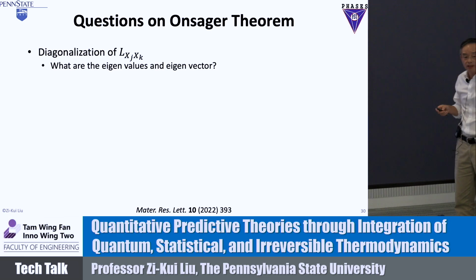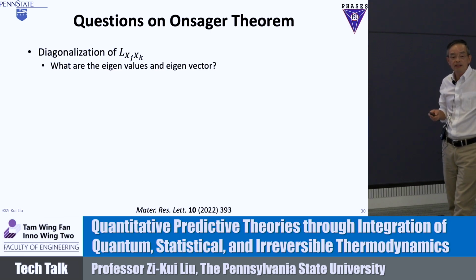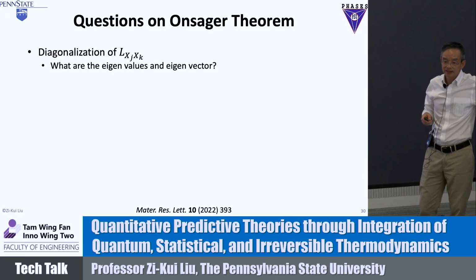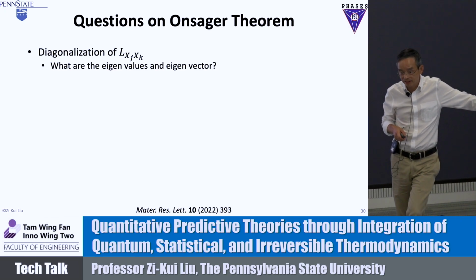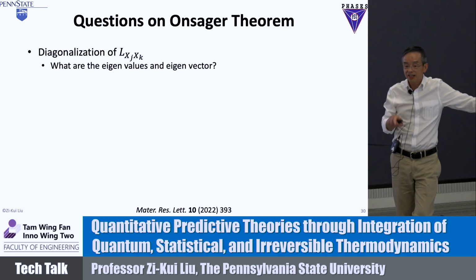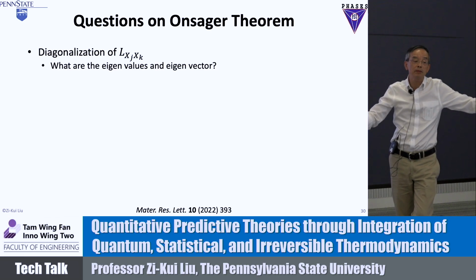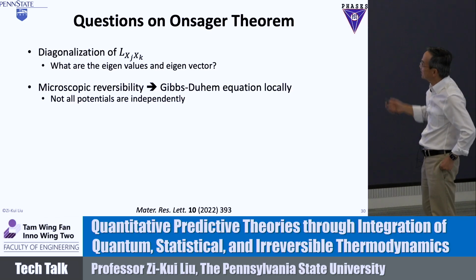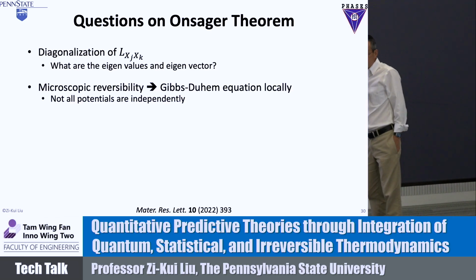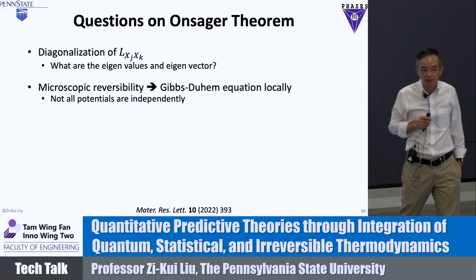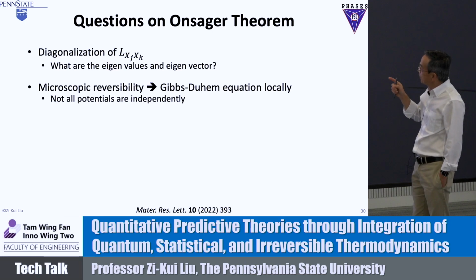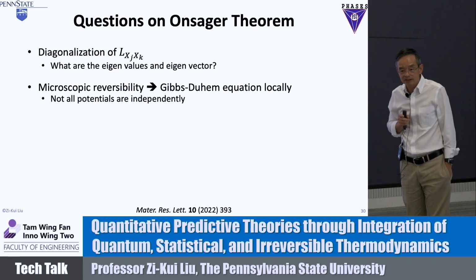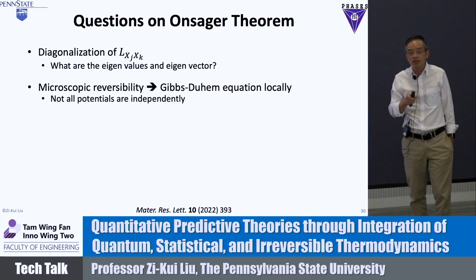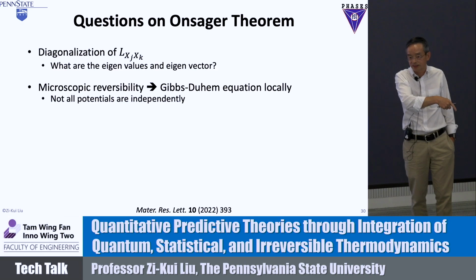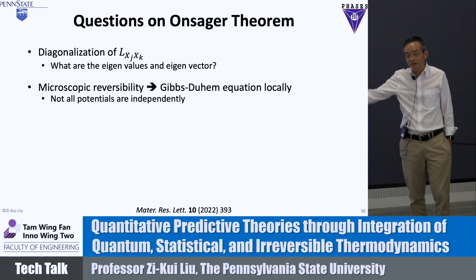The first one, is it symmetric? You can diagonalize it. So what is the result after you diagonalize it? What are the driving forces after you diagonalize the matrix? We know exactly that already from the combined law. Chemical potential drives atom motion. That means when you talk about the atomic motion of an element, it must be only chemical potential left. That's the combined law, right? That's the first one. The second one is that he used microscopic reversibility to derive that symmetrical relation. However, if you talk about microscopic reversibility, you have to apply the Gibbs-Duhem relation. If you apply the Gibbs-Duhem relation, the potentials are not independent. You have to remove at least one of them from the equation. Which one to remove? It turned out to remove every one except the only one you keep.